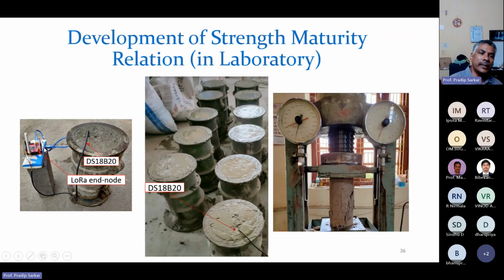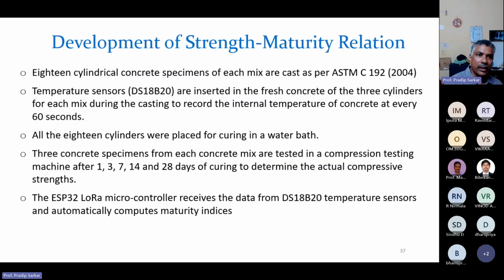And at a particular time, we see the maturity and we do the break test also. After a certain age we see what the maturity is, we do the break test and we find out the strength. So we keep the strength and maturity data, and then using this data we make a relationship.